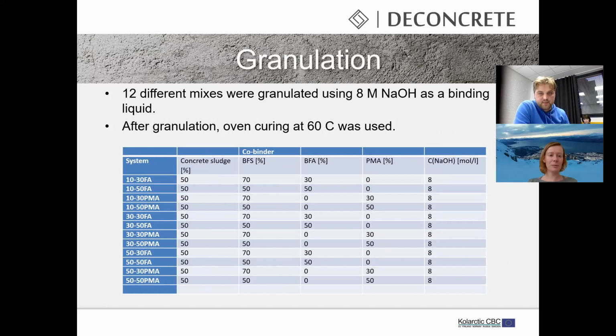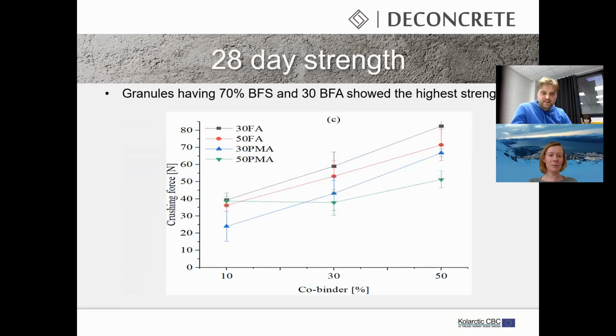This time I used 8 molar sodium hydroxide as a binding liquid in the granulation because water didn't work. And this time I only used oven curing at 60 degrees because that was the only curing method that was suitable for this material. And here are again the 28 days strength results for the granules, and I think that biomass fly ash was a better co-binder for this material. Again, there is quite a big variation, but at least with a high amount of co-binder, the granules are stronger compared to the commercial lightweight aggregates.